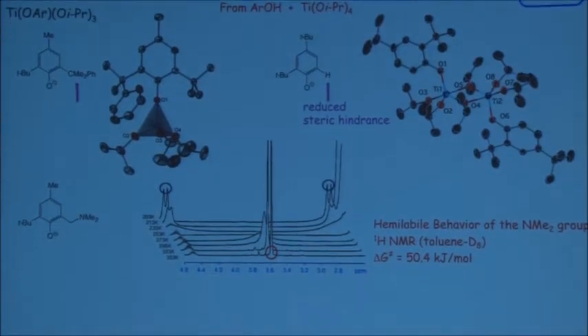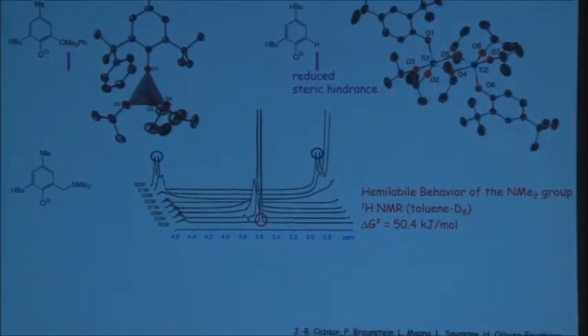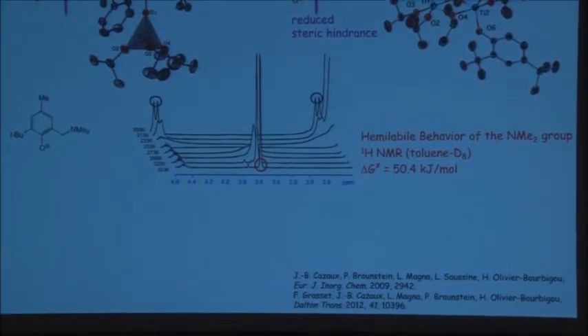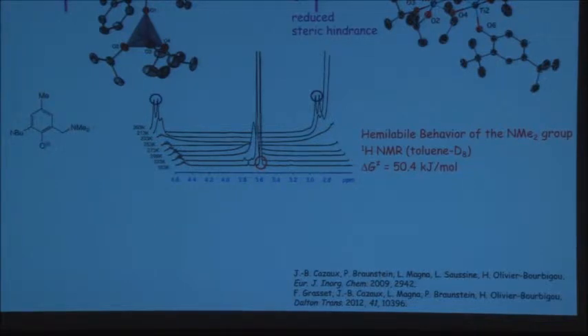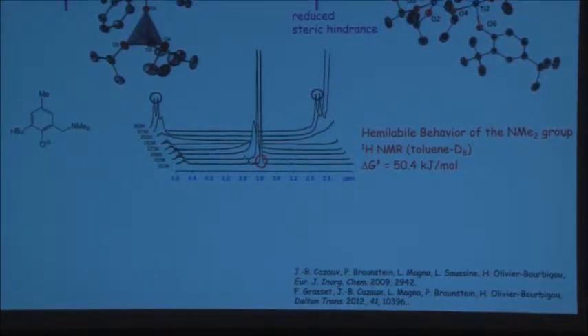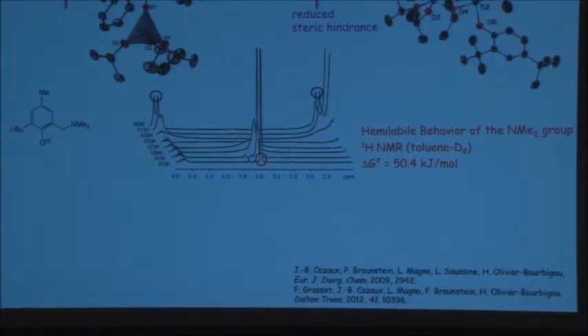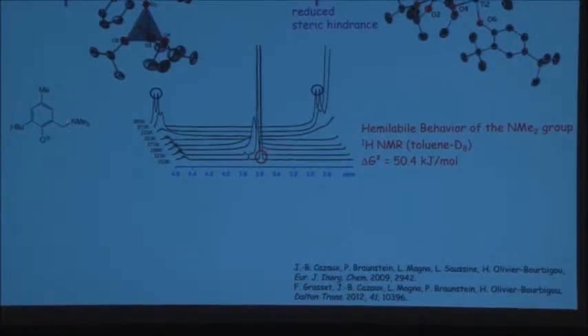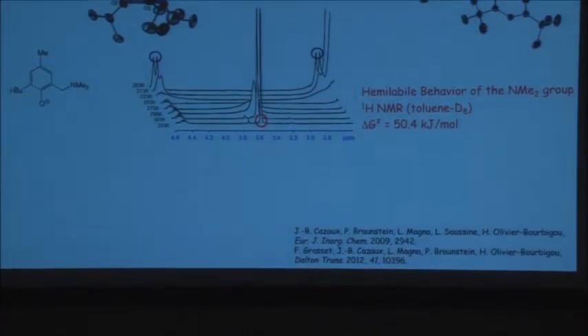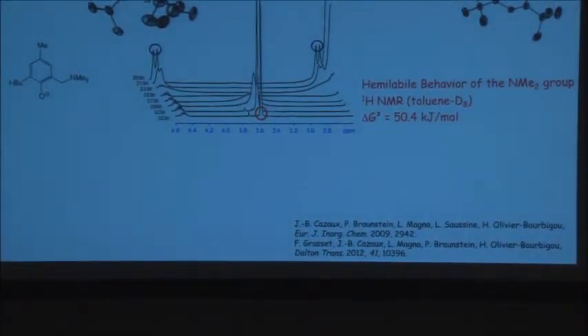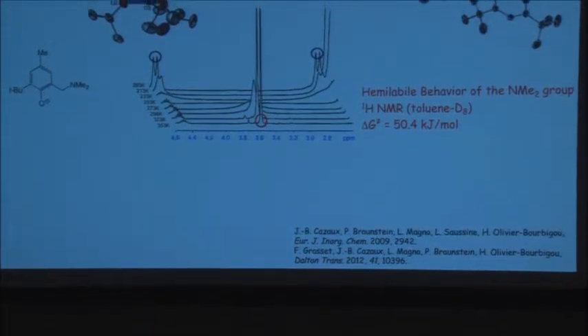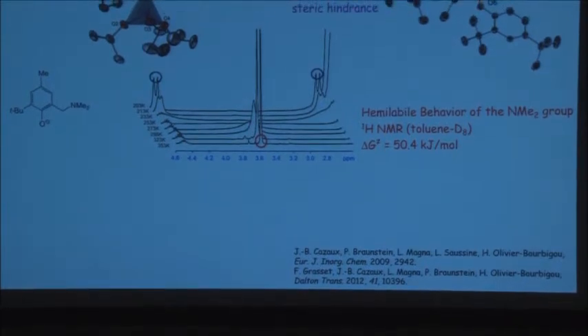Now, when we replace this group here, which is non-coordinating, it has no dative function, with an amino group here, which could potentially coordinate to titanium, although titanium doesn't like nitrogen ligands very much, but it can. We looked at the NMR, and if you look at the NMR in the CH2 region here, next to the nitrogen ligand, at room temperature, you see sort of a singlet, which splits into 2 doublets at low temperature. So 2 doublets, a typical signature of an AB system. So 2 protons become diastereotopic, you have an AB spin system, 2 doublets. But at room temperature, a singlet, which means you have here a dynamic behavior.